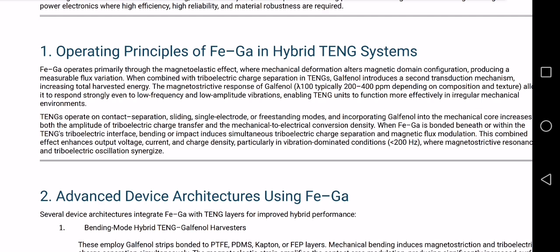Why is this hybrid system powerful? FeGa has a magnetostriction value lambda 100 approximately equal to 200 to 400 ppm. This means that even small vibrations and low frequency motions can produce a strong response. As a result, hybrid TENGs work well in the real environment, where vibrations are irregular and slow, less than 200 Hz.